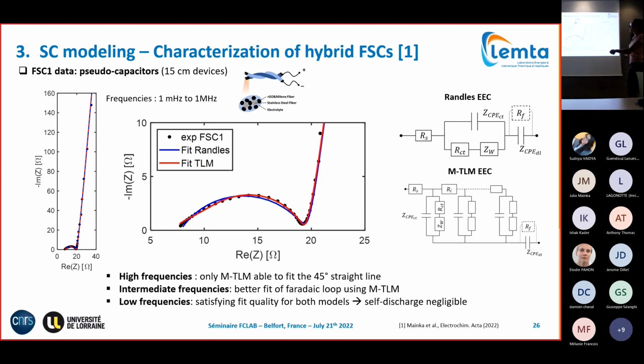Here I show you only data that stops in the positive part. If you have inductance and go to higher frequency, you will see only inductive behavior. I guess you observed it as well. Inductive behavior can be due to your connection, and if you have additional inductive behavior, this will result in an inductive loop, which can result in a deviation of your slope, so that you have lower inclination than a 45 degree slope. It means there is a contribution that comes from your electrical connection. Okay, so it's a possibility.